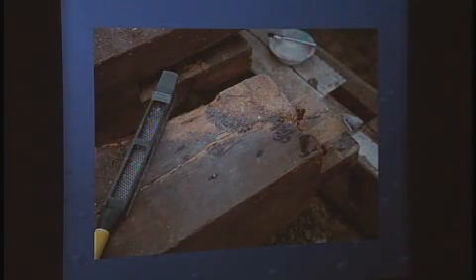And the result of that was a material that had, from a working perspective and a tool perspective, such similarity to the wood itself, I have to think that it has a better chance long haul. Now, admittedly, it's not likely that you're going to be pouring this into panel paintings, but it is a useful thing to learn. And I can tell you that several years after the fact, this repair has remained intact with no fracture along the glue margin whatsoever.